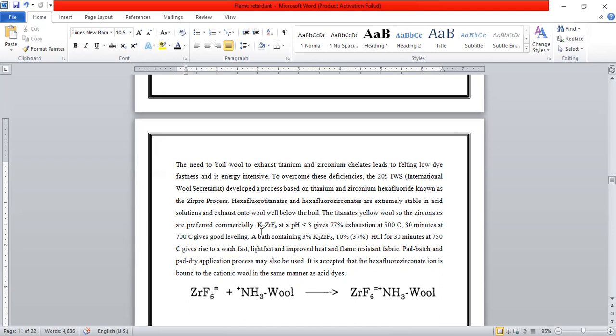Potassium fluorozirconate at pH less than 3 gives 77% exhaustion at 50 degrees Celsius and 30 minutes, and at 70 degrees Celsius gives good leveling. A bath containing 3% potassium fluorozirconate, 10% to 37% hydrochloric acid for 30 minutes at 75 degrees Celsius gives rise to a wash fast, light fast, and improved heat and flame resistant fabric. Pad batch and pad dry application processes may also be used, and it is accepted that the hexafluorozirconate ion is bound to cationic wool in the same manner as acid dyes.